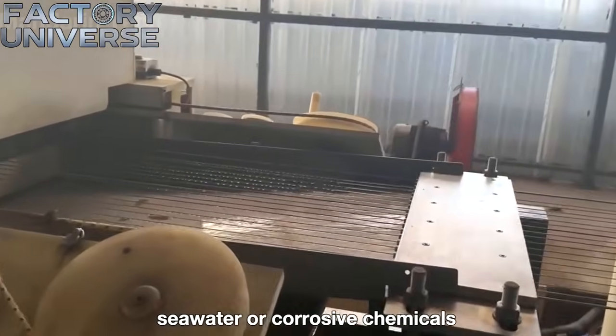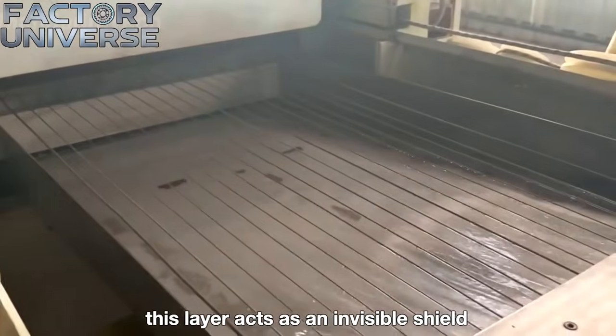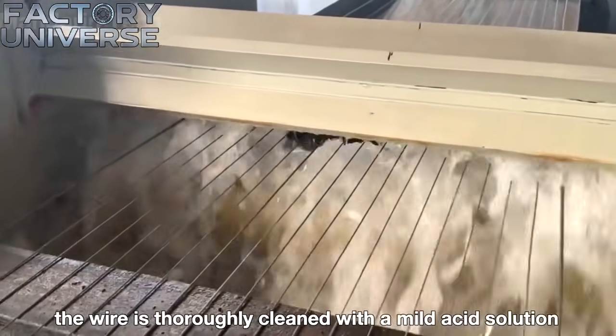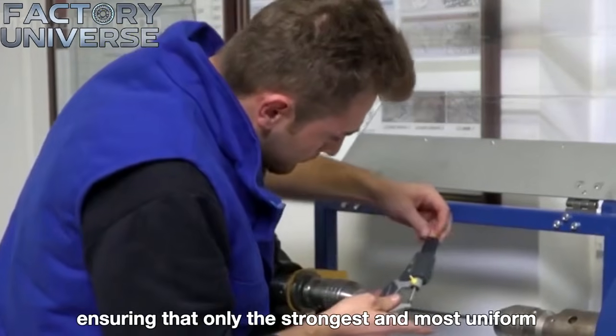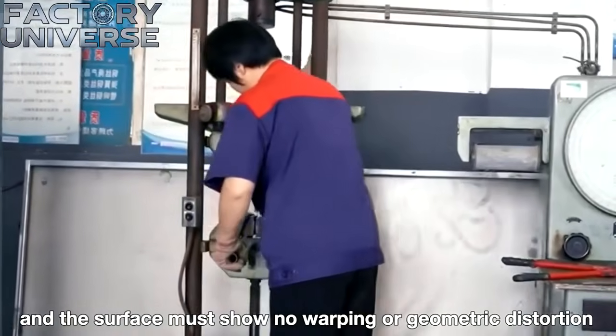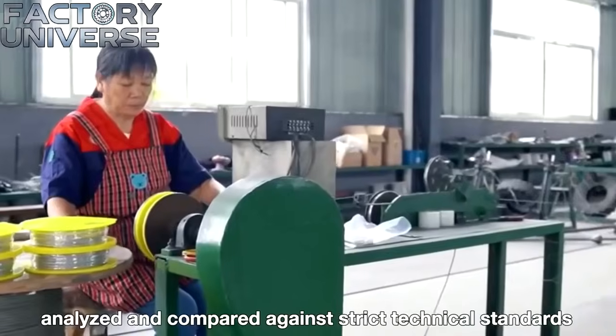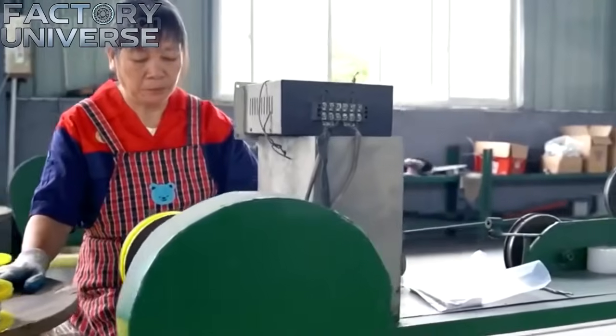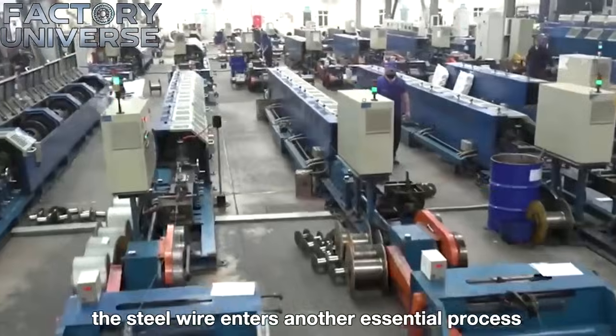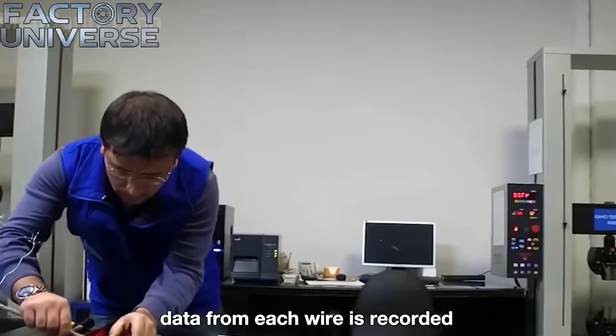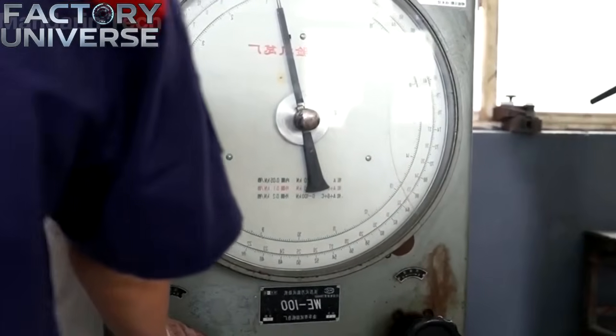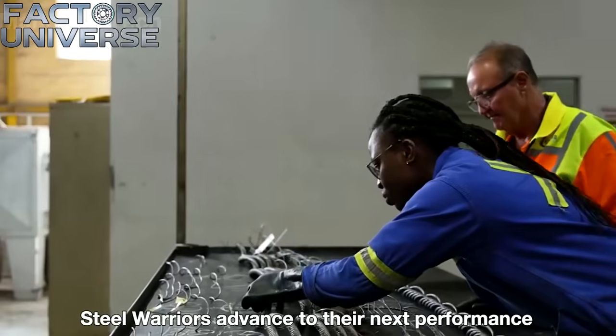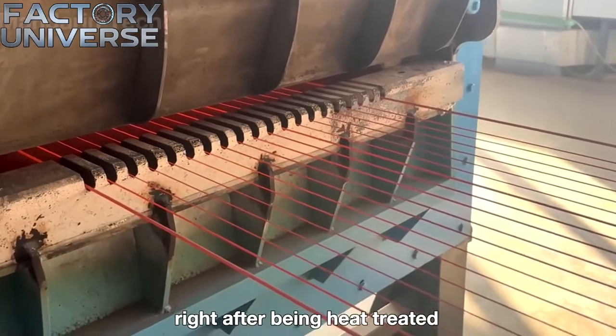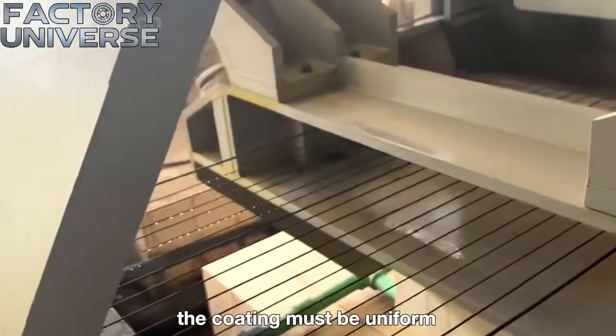The wire passes through a preparatory cleaning phase where a mild acid solution strips away every trace of grease, industrial dirt, and microscopic rust. It is visible how the metal surface transitions to a pristine state, ensuring the subsequent coating achieves a molecular bond. At first glance, the dipping process looks like a simple submersion, but in reality, the molten zinc bath or polymer extrusion system requires absolute synchronization of temperature and pressure. The equipment gradually coats the moving strand, maintaining a uniform thickness that must be entirely free of air pockets or microscopic gaps. One can notice how the coated wire emerges with a consistent metallic or synthetic sheen as it moves toward the next level of processing. The process is only gaining momentum.